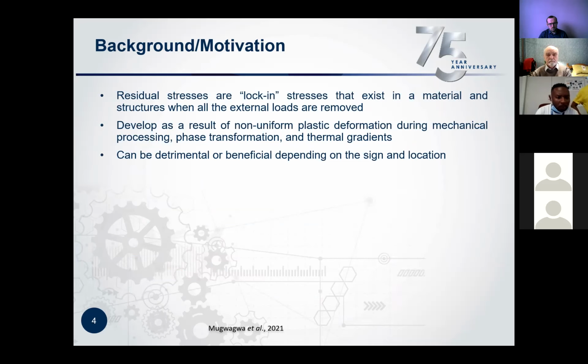For some of you that are not so familiar with residual stresses, by definition, residual stresses are the locked-in stresses that exist in the material and structure without an external load applied to it. They remain even after processing. They develop as a result of non-uniform plastic deformation during mechanical processing, or phase transformation, or thermal gradients during manufacturing. The stresses can be detrimental or beneficial depending on their sign and location on the component. Compressive stresses are likely to improve your fatigue resistance, while tensile stresses can have a negative effect on your mechanical properties.